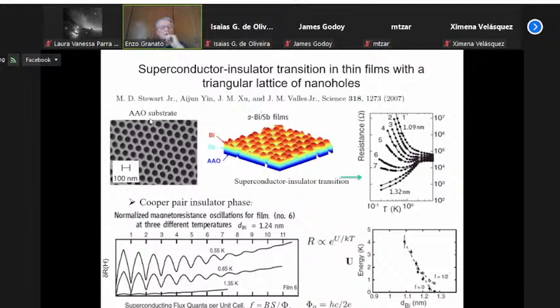The template is sketched here on the left. This is an anodic aluminum oxide substrate. The film is deposited on the template, and the film takes the form of the template, but with height variations. There are large bumps at the nodes of this substrate, and therefore the bumps form a honeycomb lattice of regions. If you study the resistivity of this system as a function of temperature and thickness, as you decrease the temperature, for some samples the resistivity tends to go to zero, while for other samples the resistivity increases. As you decrease the thickness, there is therefore a superconductor-insulator transition at some particular critical value of the thickness.